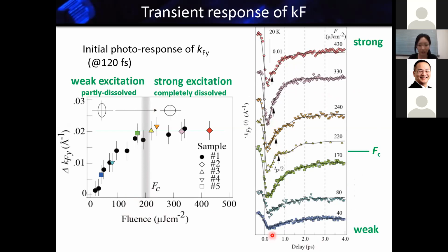And this is the time-dependent curve of the Fermi momentum. When weakly excited, the Fermi momentum changes a little bit and recovers. When you increase the excitation fluence, the change becomes larger and larger, and at some point it starts to oscillate like this. When you go to the stronger region, the change of the Fermi momentum saturates, but it's a little hard to see that there's a small oscillation component here. So we try to extract these oscillation components and figure out what's happening.